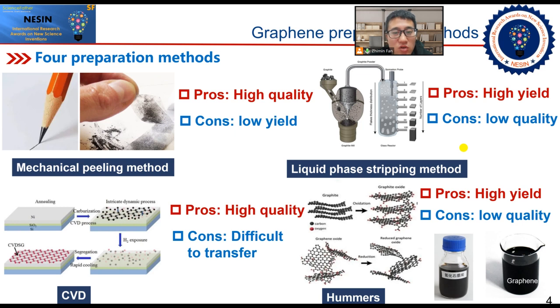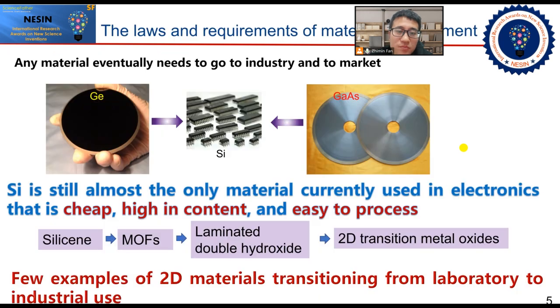There is also the redox method, which is often referred to as the Hummers method, which is a top-down method where graphite is first oxidized to graphite oxide, exfoliated, and finally reduced to obtain graphene. This is the method commonly used in laboratories and many domestic companies, but the graphene produced by this method has many defects and the performance is very low. But as a material, it must eventually go to industry and the market so that the material can benefit mankind.